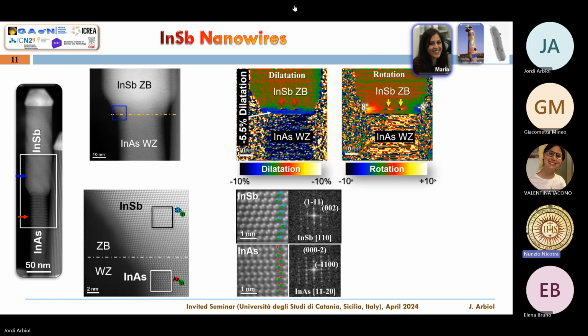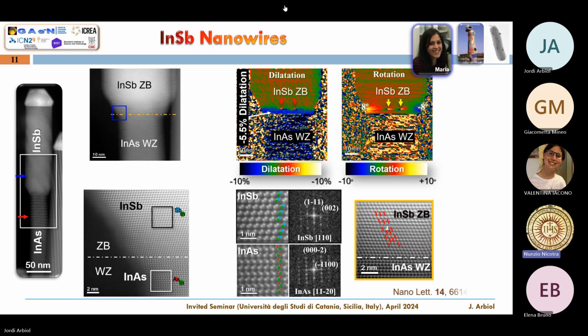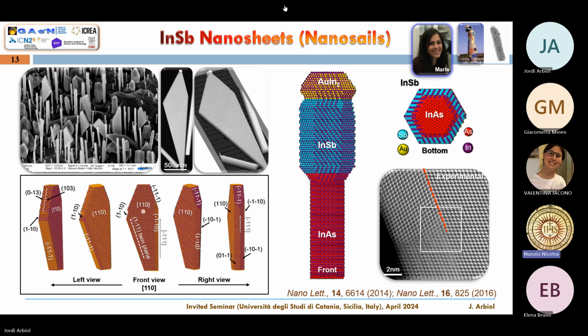So this is a really nice way to grow materials with high purity, because if you grow a nanowire, after the first, let's say, nanometers, when everything is super strained, you have a perfect growth with the material fully relaxed. What you can see here in this picture, this is a rotation map. You see that on both sides at the interface, there is a plus minus 8 degrees rotation of the planes. And this means that there is a kind of plastical relaxation. So the material tries to adapt. One way to adapt is with elastic relaxation. And here you can see how there are misfit dislocations, one here and another here. But also there is a competing force of relaxation methods competing the plastic relaxation with elastic relaxation. Okay, there is a combination of relaxation mechanisms until the material just grows without any other defect. So this is what happens with the normal nanowire.